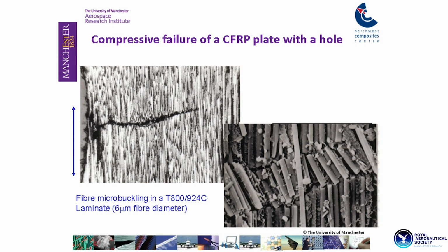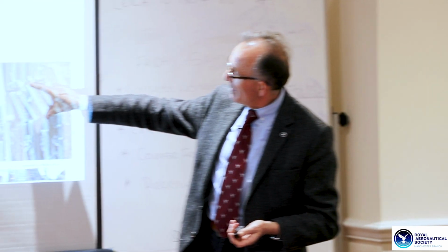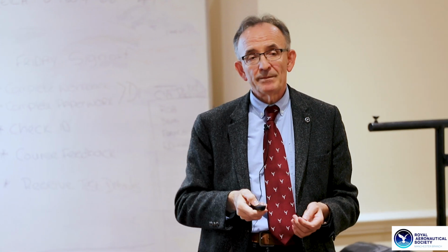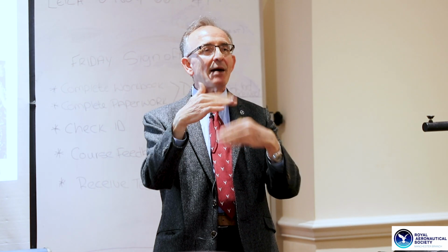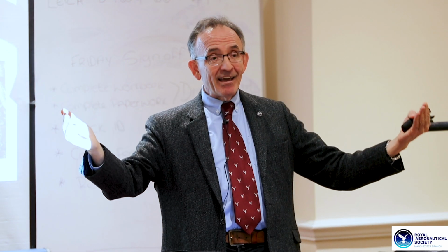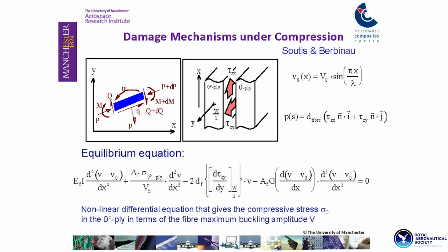Fiber diameter is about 6 micrometers. So this length here is about 10 fiber diameters. And when that crack reaches a critical length of about 2.5, 3 millimeters, depends very much on the layup and the stacking sequence, then it propagates catastrophically and you cannot arrest the crack.